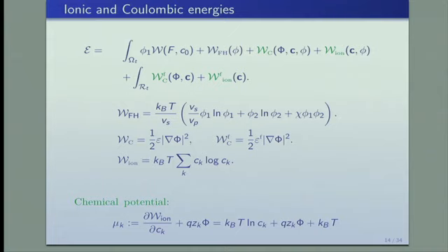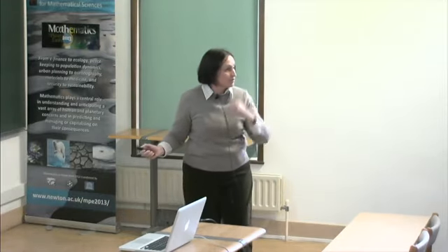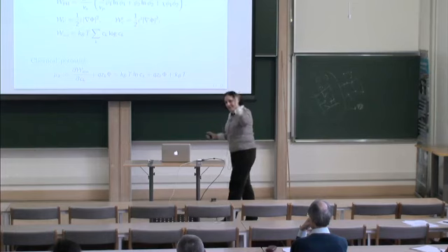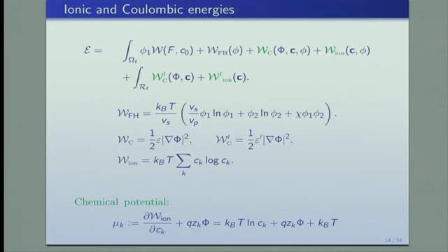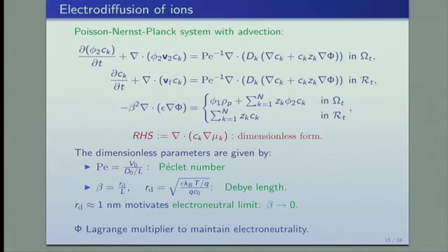And then, of course, very important is the chemical potential, which is basically a potential energy. It has the same role as the gravitational energy with a change in height, right? So you store energy or you release energy, and in this case, you store or release energy with this potential according to this function by changing the number of particles, in this case by changing the concentration. So changes of concentration in a way act as changes of height in, say, gravitational physics. Okay, so now here we postulate the Poisson-Nernst-Planck equations.